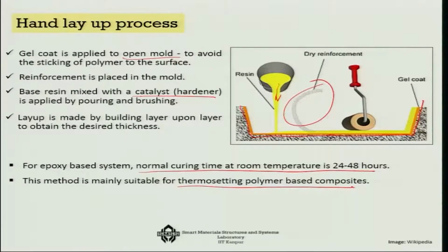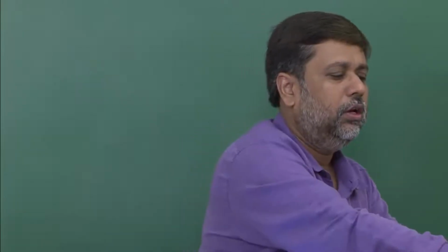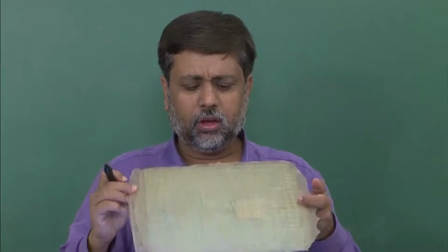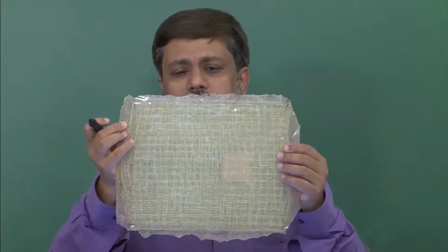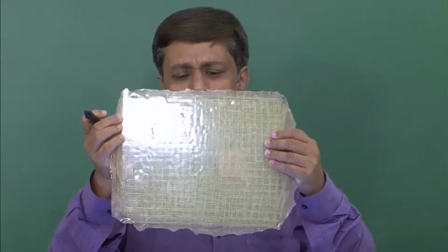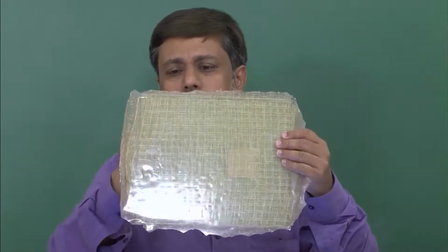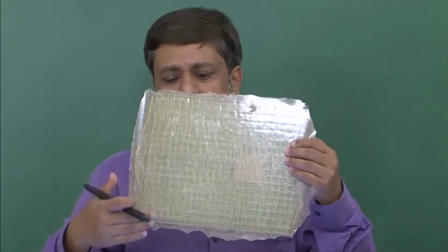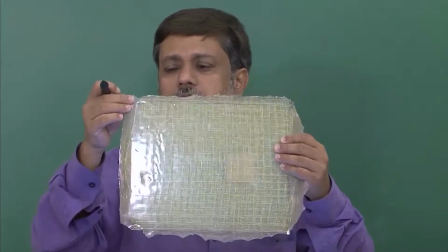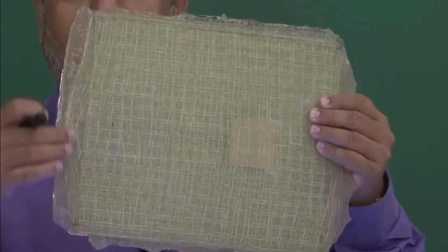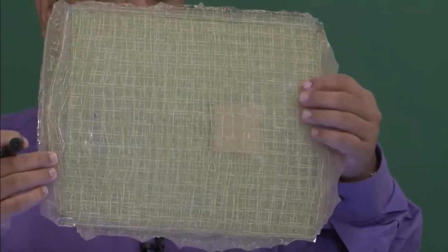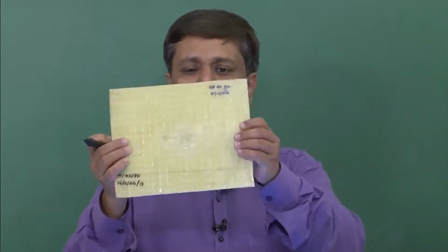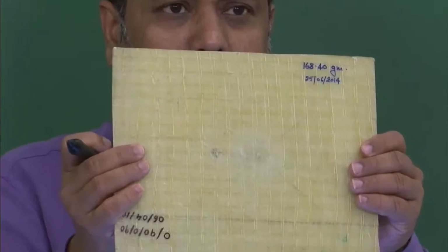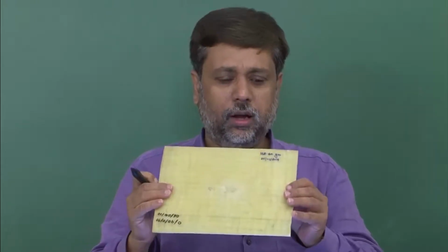For example, here I can show you one composite that we have developed in this manner. As you can see, there are several layers. This is a flat plate, so there are long layers as well as cross layers, several such layers over which we have applied resin, and you can see the extra resin at the ends of it. Once it gets hardened, you cut it into a piece like this. This is a glass fiber reinforced plastic. You get this through the hand layup process.